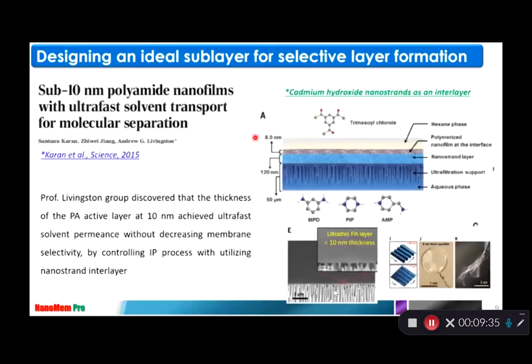impact journal Science. They mentioned that sub-10 nanometer polyamide nanofilms with ultrafast solvent transport for molecular separation will give very good overall performance of the membrane. So Andrew Livingston discovered that a polyamide thickness of 10 nanometers achieved ultrafast solvent permeance without decreased membrane selectivity, by controlling the IP process utilizing a nanostrand interlayer. So this is their study.